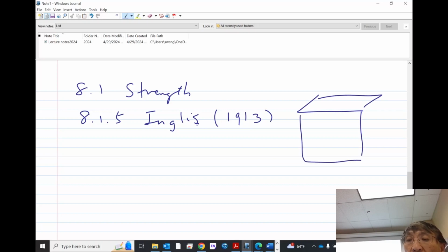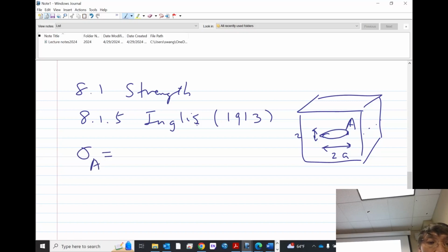It's a theoretical calculation. It considers an infinite elastic sheet, and he digs an ellipsoid-like hole. And this hole goes through the entire thickness. And it's an ellipsoid, so we have the longer dimension as 2a, smaller dimension as 2b. And he says the stress at these 2 poles, let's call it A, is stronger. So this is a sheet you are stretching like this with the stress of sigma, and it says it's stronger by 1 plus 2a divided by b.